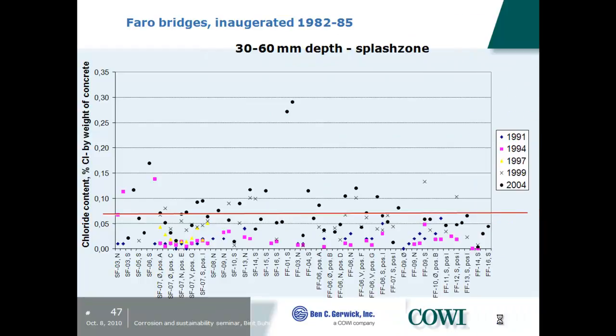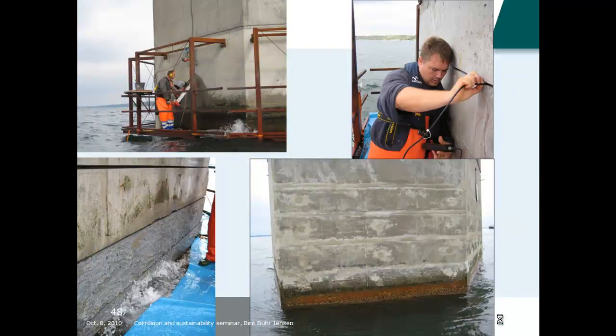Before deciding to do cathodic protection, we had a lot of dust samples for chloride during the service life of the structure. They were built in 1982 to 1985, and you can see we did the dust samples throughout the service life. And when you look down here, these are just the pier numbers. You can clearly see that the chloride concentration increases at the depth of reinforcement in the splash zone. Having a threshold level even at 0.065%, even with uncertainties as you have here, clearly a lot of these chloride concentrations exceed the threshold level. Those 2 bridges now have a cathodic protection installation with sawn slots where an anode ribbon is placed in these slots.